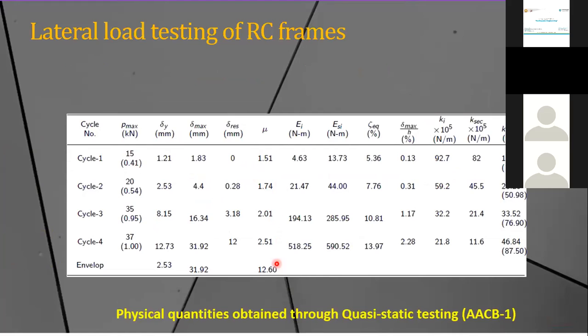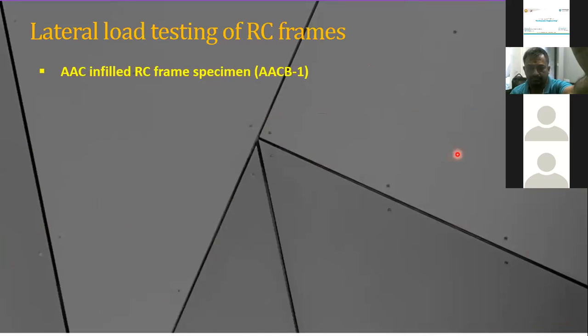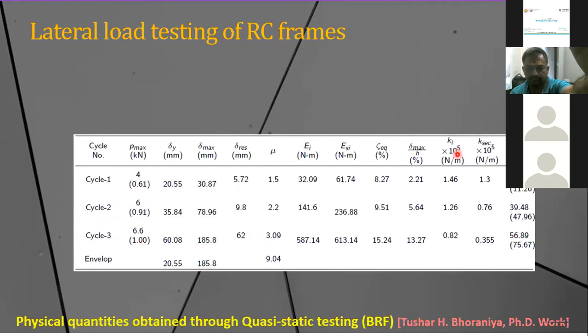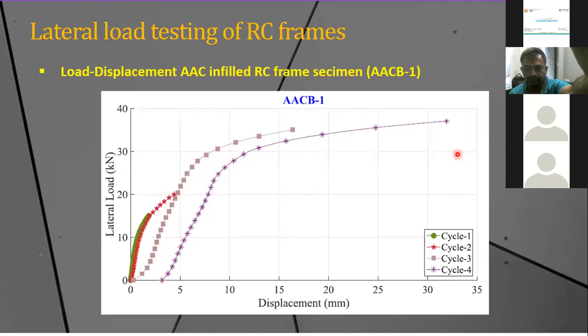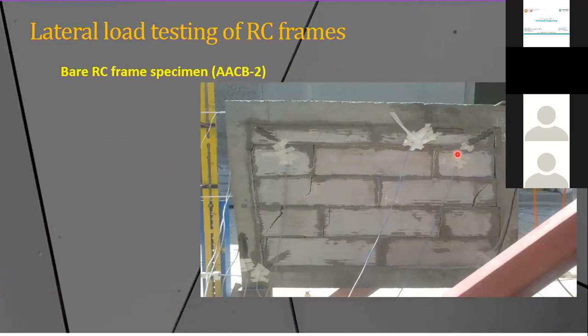Here also you will find that with the AAC block, the displacement capability is good, around 12.60, and the stiffness degradation is also increasing with the lateral loading. But most important, it has a good initial stiffness. If you look at the previous one, the stiffness was very low, as you can see 1.46, but here you can see the stiffness is very large. So the masonry infill has definitely improved the stiffness.